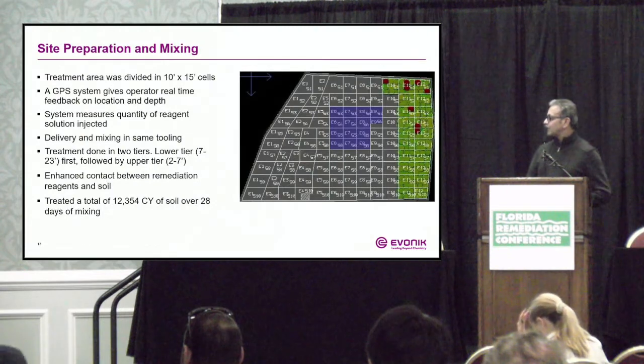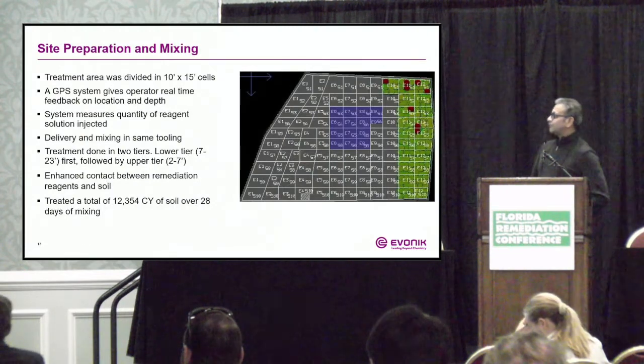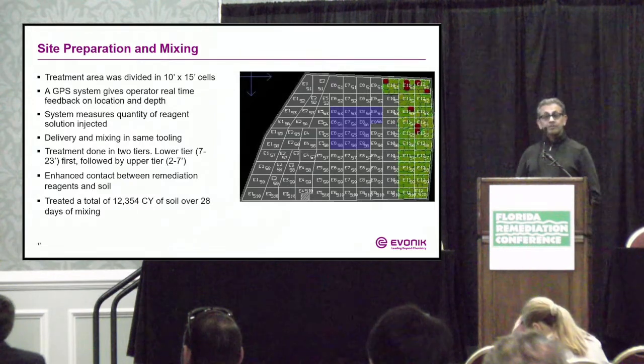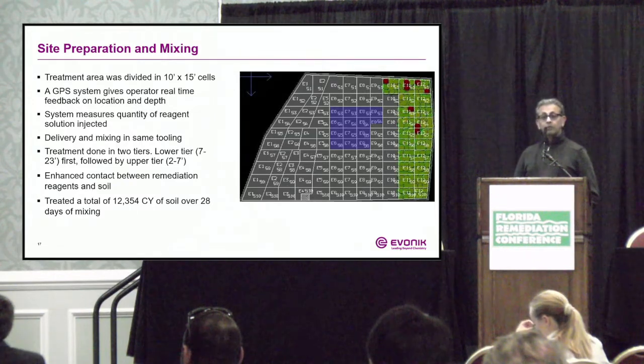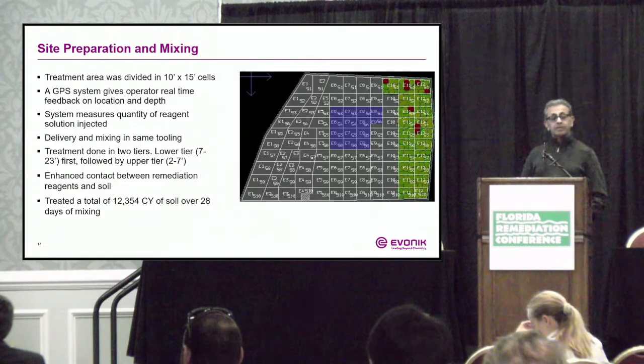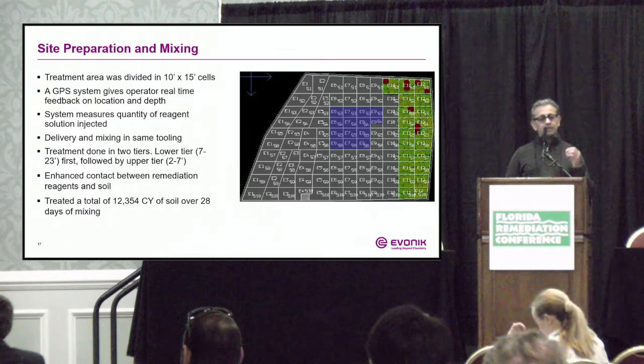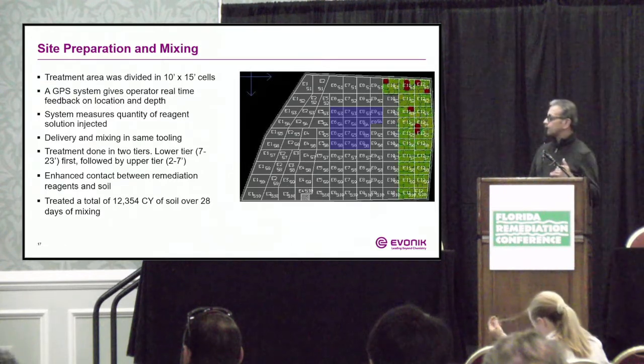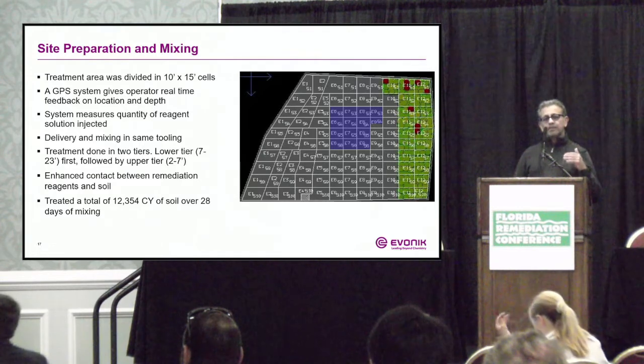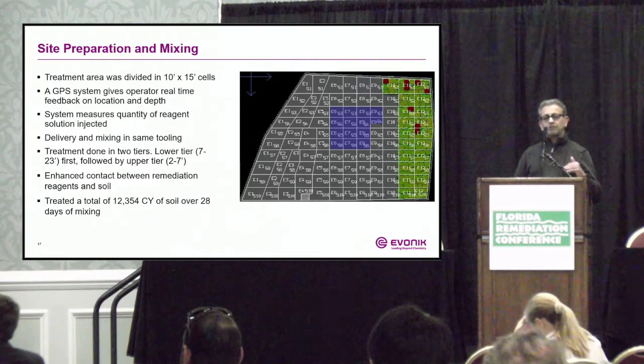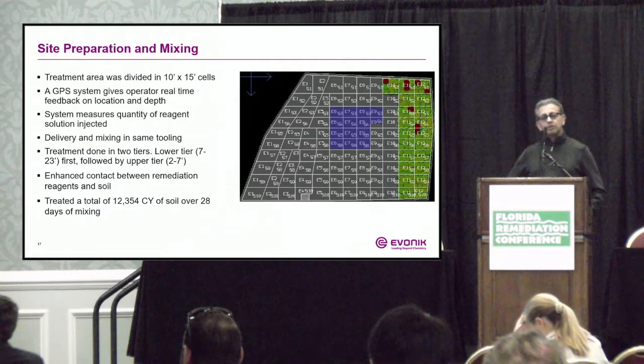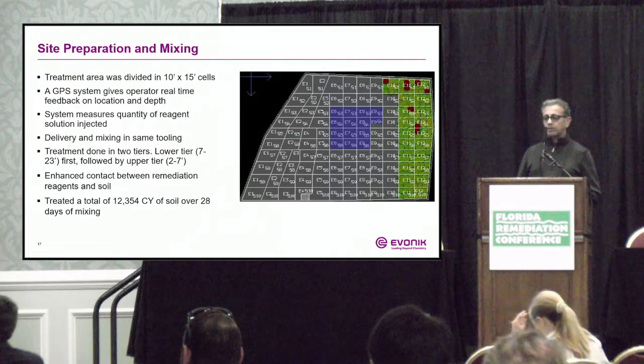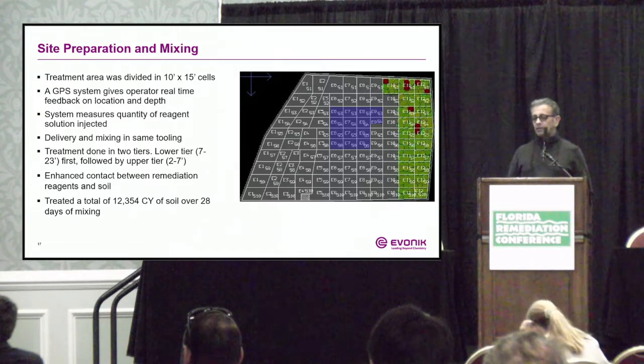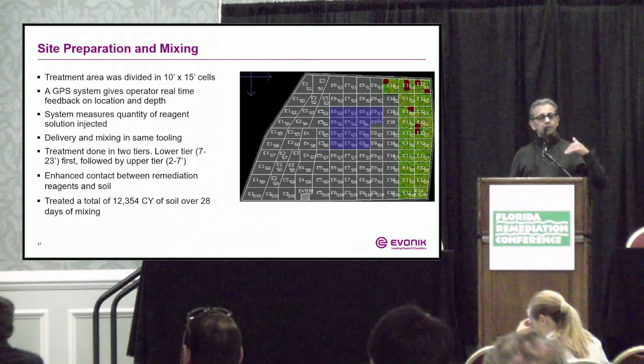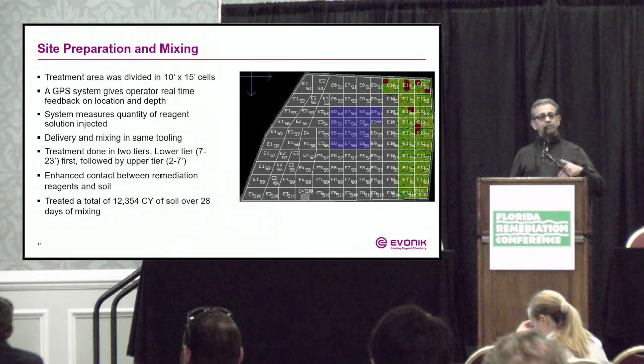Site preparation: the whole area was divided into treatment cells, 10-foot by 15-foot cells. An onboard GPS system gave the operator the precise location and depth. The system was also in place to measure the exact amount of Portland cement and persulfate being injected. Delivery and mixing were done in the same tooling, so it wasn't separate. Everything was done simultaneously. Treatment was done in 2 lifts, 2 tiers. The lower tier was treated first, from 7 to 23 feet below ground surface, and then the upper tier was treated later on.